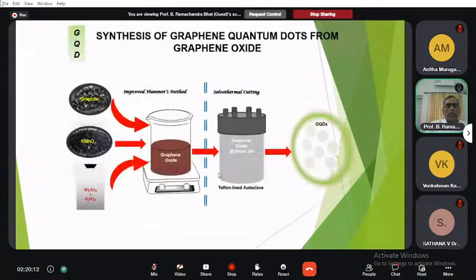And coming to the synthesis of graphene quantum dots through the hydrothermal method. Taking graphite, and then potassium permanganate, then sulfuric acid and phosphoric acid. It's an improved Hummers method for the synthesis of graphene oxide, and then the solvothermal cutting is possible. With graphene oxide at basic pH, it is cut into smaller pieces, and this is nothing but the graphene quantum dots.